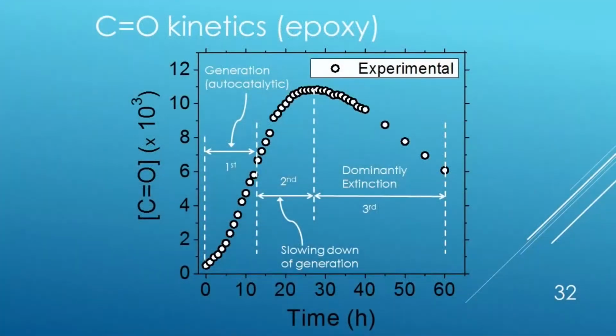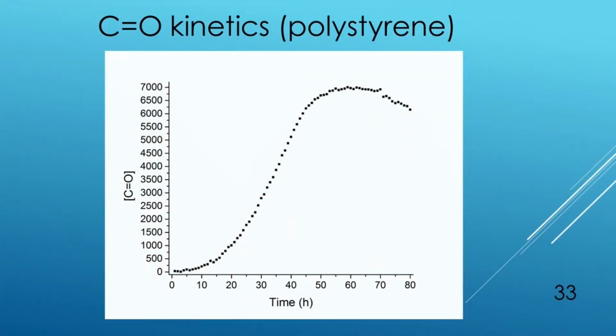That's because carbonyls now are dissociating, okay? So, this was still a very hypothetical explanation. We see three different regimes there. The first regime is the autocatalytic fast regime, where carbonyls are producing carbonyls. In the second regime, the thing is getting slowed down because oxidation sites are all depleted. And finally, carbonyls transform to carbon dioxide, carbon monoxide, water. That's the dissociation regime. Now, the same thing is seen for polystyrene. For polystyrene, Lynchy got this data. We see the same sigmoidal behavior, more pronounced. We see a more nonlinear response in the beginning, which says carbonyls are producing other carbonyls.